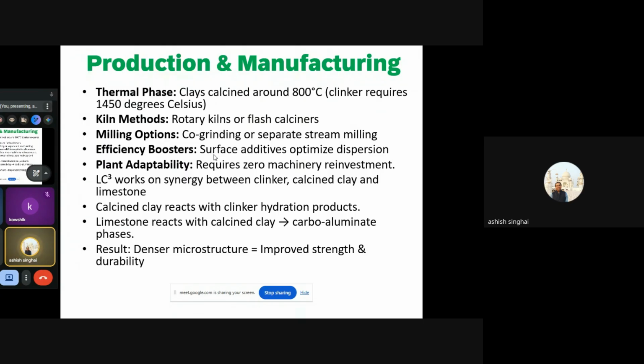Efficiency boosters: surface additives optimize dispersion. Suppose somebody wants some additional additives, they can be added to optimize the dispersion of the materials. Plant adaptability requires zero machinery reinvestment. That means with the existing setup, you can produce and manufacture LC3 cement. And what is the result? Denser microstructure, improved strength and durability. As we all know, because the three different elements are ground finely, the microstructure of the cement becomes so fine and so densely integrated with each other that, talking about the concrete, strength is increased because of the better cohesion and better interlocking of particles, and hence the durability is also improved.